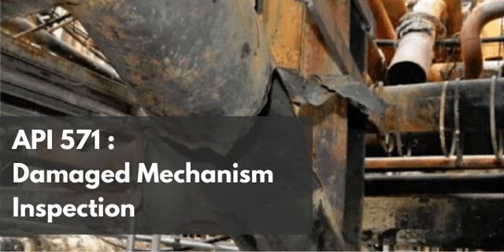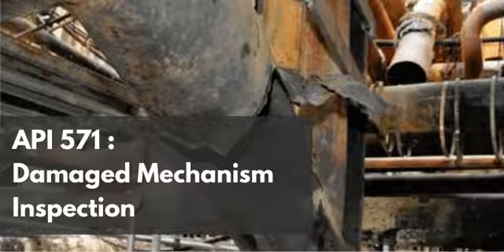So, look around your facility. Consider the hundreds of miles of piping. How many seemingly safe, robust systems operating at low amine concentrations might be sitting on the absolute edge of fracture simply because a tiny, undocumented attachment weld made 20 years ago skipped that critical 1175-degree relaxation bake? It really is the invisible history of the metal that dictates the future of your asset.